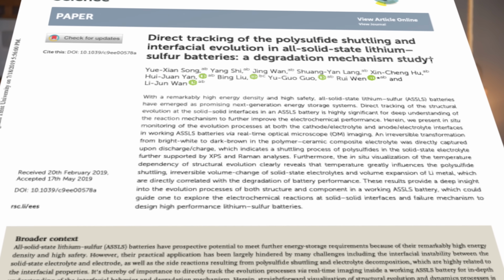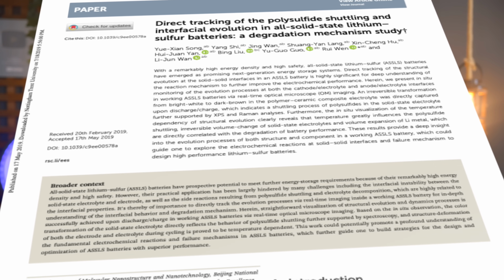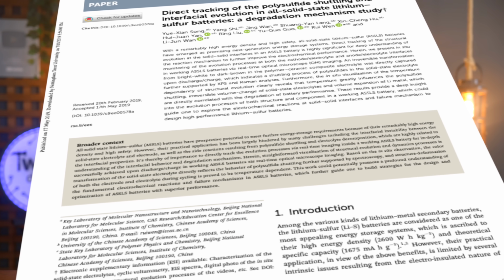A solid electrolyte is supposed to avoid this completely, but I found at least one published paper where the authors prove that it can still happen even with solid electrolytes. Now this can limit the cycle life of the ASSLS battery to only a couple hundred cycles. That means charge and discharge only a couple hundred times. Low cycle life means the battery dies sooner and you have to replace it more frequently, adding more maintenance and